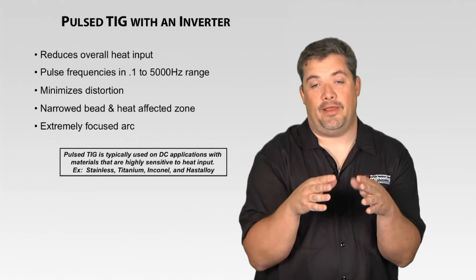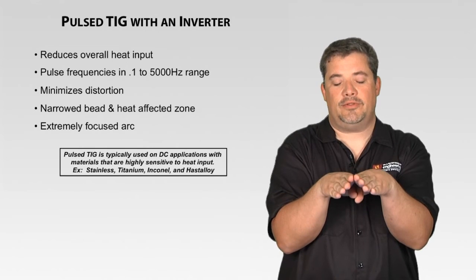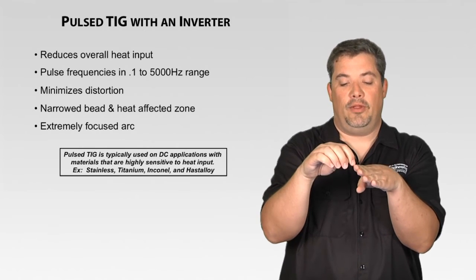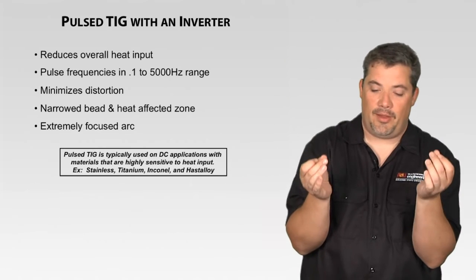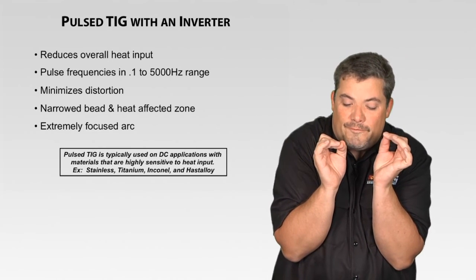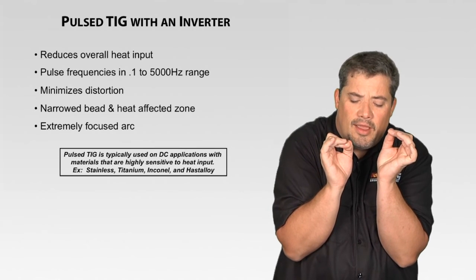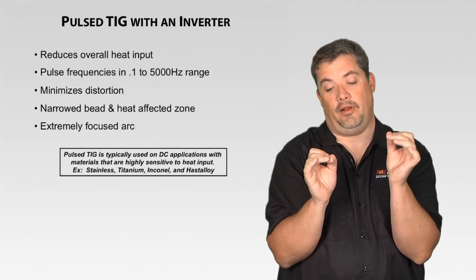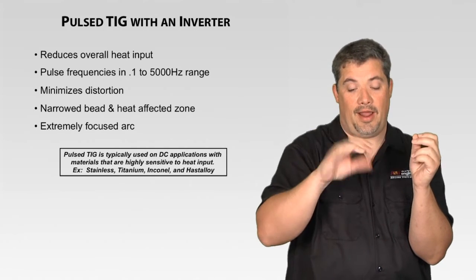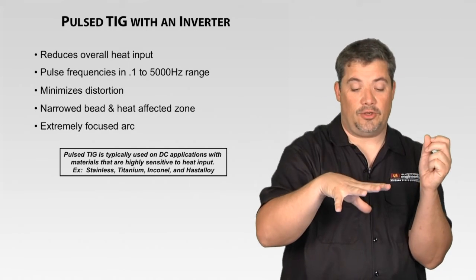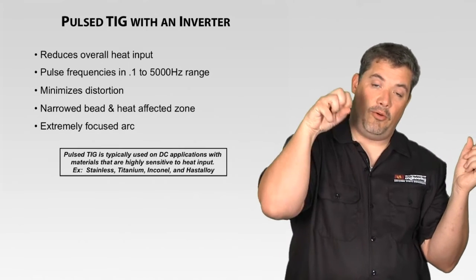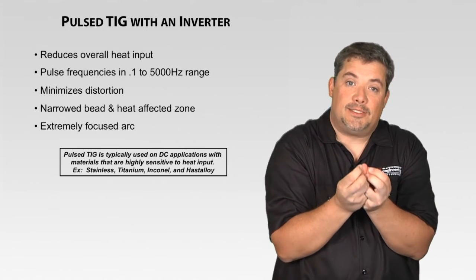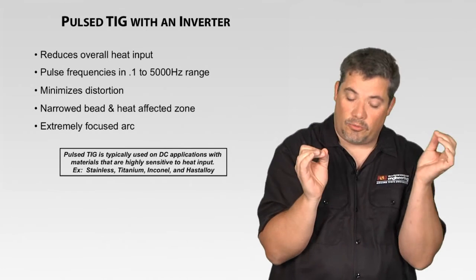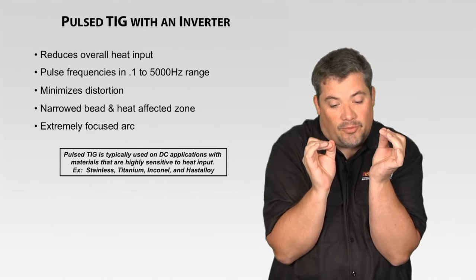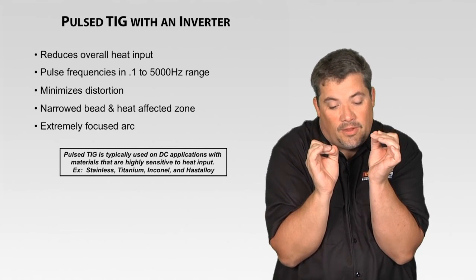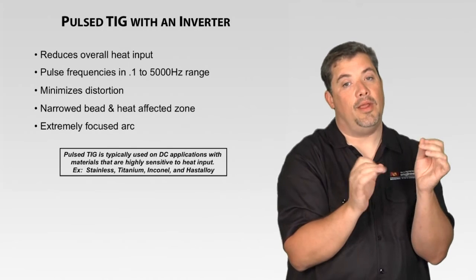The best example I could give you, and you'll see it in lab at some point, is if I do an outside corner stainless steel TIG weld, and I'm doing really thin stainless, the only way I know how to describe it is it's like going from this, where I'm really focused, where I gotta be everything perfect when I'm steady, but if I turn that pulser on, I can actually relax a little, and it's a lot easier to make that weld. That hot, cold gives me enough control to melt that filler rod, but that low amperage side keeps that bead nice and small, so that hot and cold just gives me more control to make a nicer looking weld. Again, it's like going from being really focused, all hunched over, tight looking, to actually being able to relax a little bit and make that weld more efficiently.